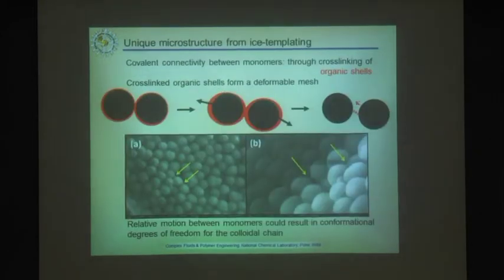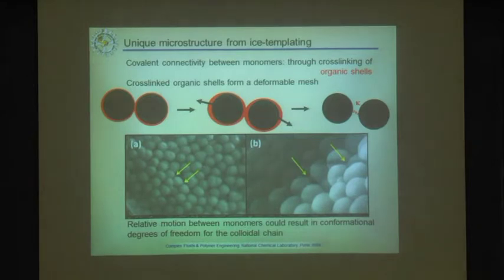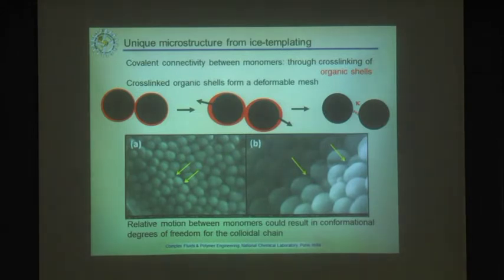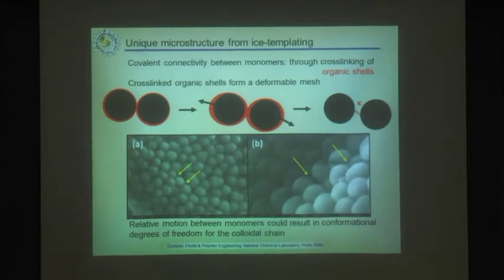So what we believe is happening is that if you cross-link something in the frozen state, you set up some kind of unique structure which we don't fully understand as of yet, which doesn't have to do with the number of crosslinks, but maybe has to do with the spatial distribution of crosslinks in this material, that gives rise to some kind of an effective elastic bonding between these colloids. So it's really a way of creating an unusual bond in these systems. We've done things like FESEM, and it's not very clear that we can pick up anything here.